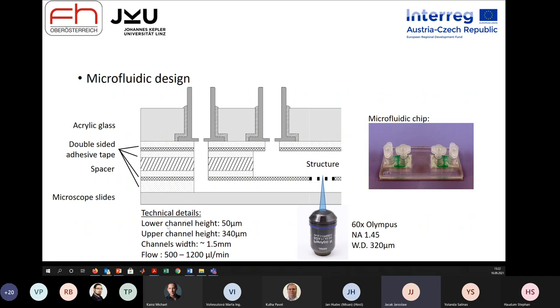So that was an important issue. If you look at the technical details, this is about the height of the channels here and the flows that we were able to achieve. And in this case, I have to mention that we only had flow on top, which was continuous. In the bottom, the cells did not require it, because if you imagine, this was more or less part of the blood vessel. So there were the cells like, for example, HUVECs, which are in the first contact, let's say, to the flow. And in the inner channel, these were the cells which are either muscle-like cells or pericytes when it comes to the blood-brain barrier, which basically stabilize the endothelial cell layer.